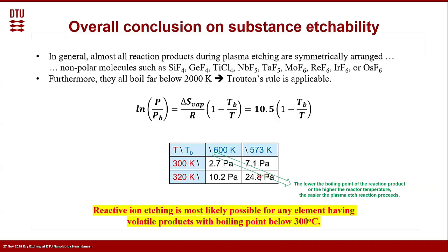So it means that my reaction can go relatively fast already. The reaction pressure, so the vapor pressure, is directly correlated to the flux. If you remember from the gas theory, the flux and the pressure are related. It is the flux of my species which are going to be in the vapor phase, or my etching species. So it's the etch rate. This means our etch rate is already sufficiently high to make sure that it works. If you go now for materials with a slightly higher boiling temperature, in this case almost 330 degrees, you can already see it's 2.5 times slower. This will still work.